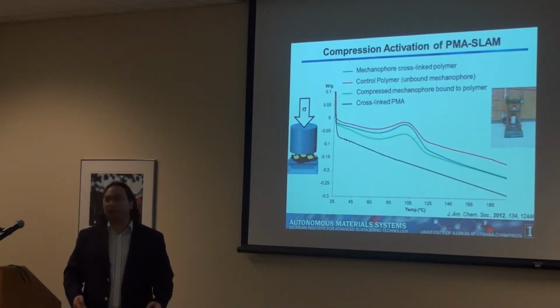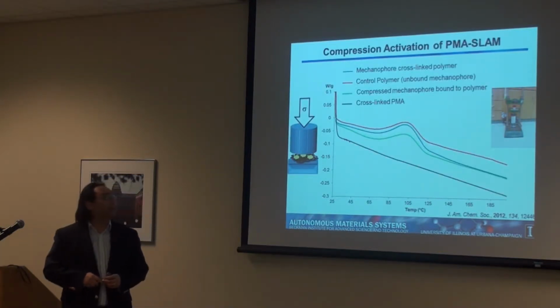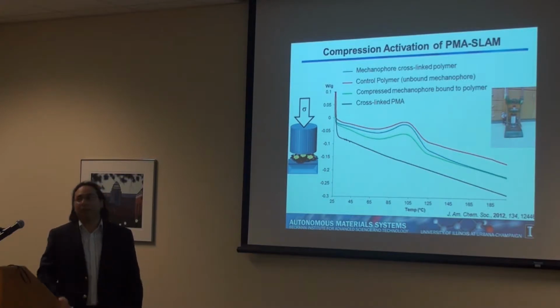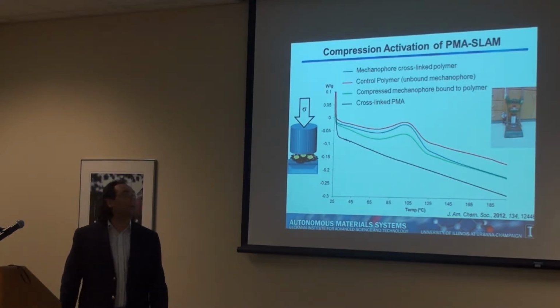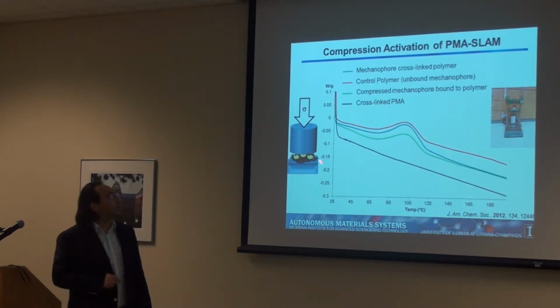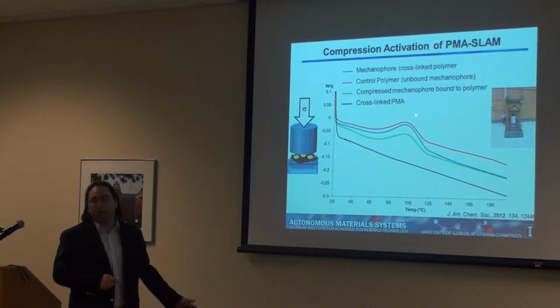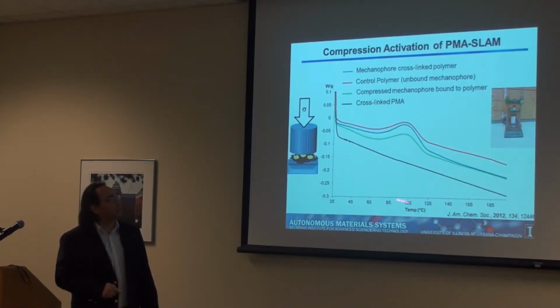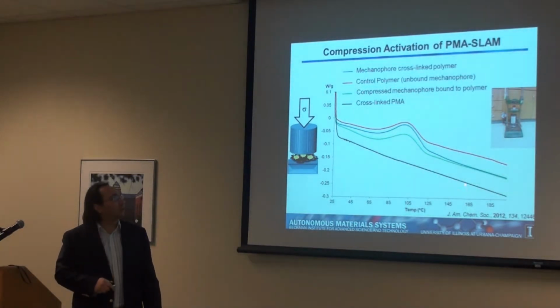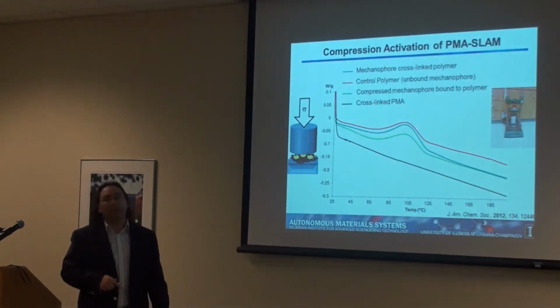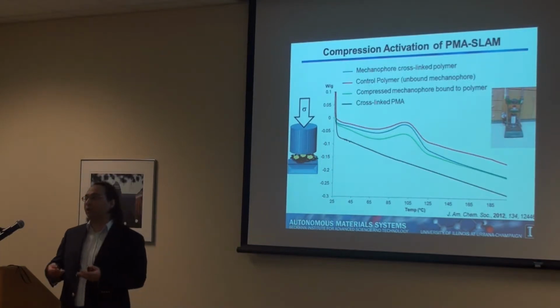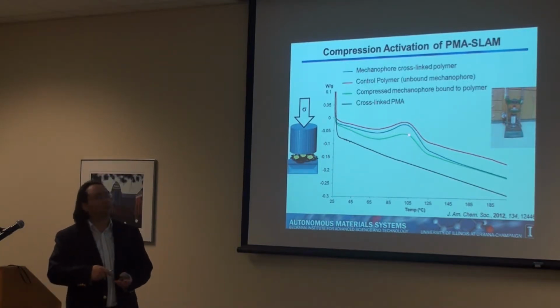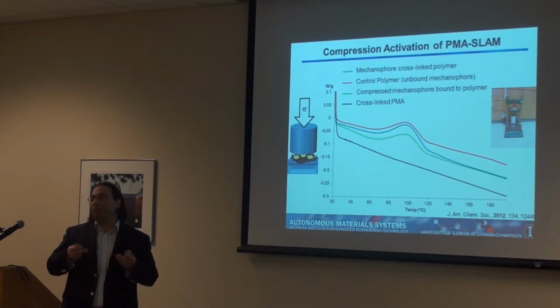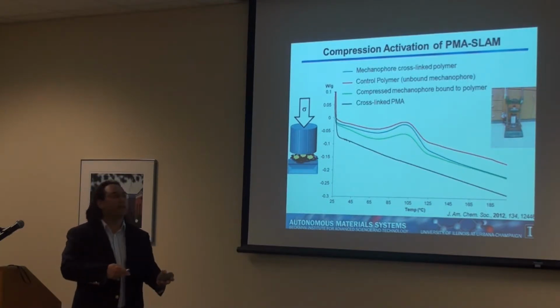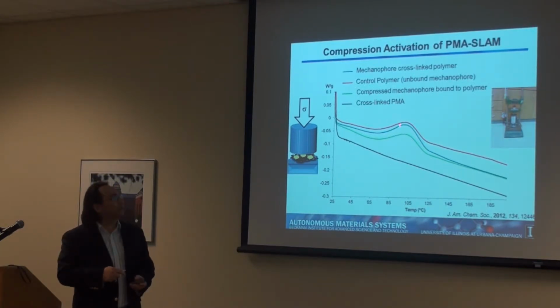So in order to analyze our material, we use DSC. Basically, it's a calorimetric analytical system. If I have, for example, just polymer PMA and I change the temperature, you just see this common change. But if I have something that releases energy when it undergoes a chemical reaction in there, as the temperature goes up, at some point I'll reach a temperature at which the reaction will occur, and it's going to release energy. So you see a peak.